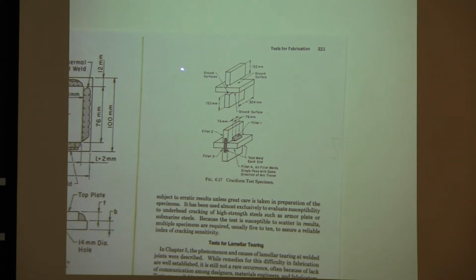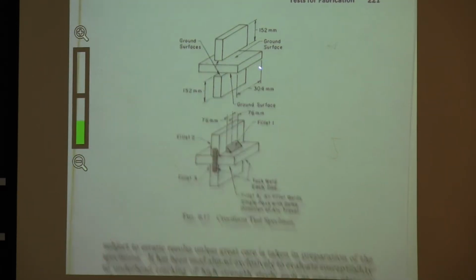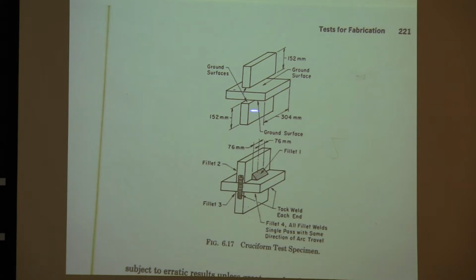Very, very sophisticated test. Another one was the cruciform test. These are kind of like 50, 60-year-old tests, where you basically take 3 plates and weld them together on the ends, and then you put a fillet weld here, a fillet weld here, a fillet weld on the other side. And the 4th one is the one with the highest restraint, where the plates can't move, and that's the one you look for the cracks. Okay? So with relatively small pieces that are not 2 inches thick, you can use a half-inch thick cruciform plate, and you can get yield level stresses on the type of steel you're interested in, whatever your electrode is. Okay? Pretty crude tests.